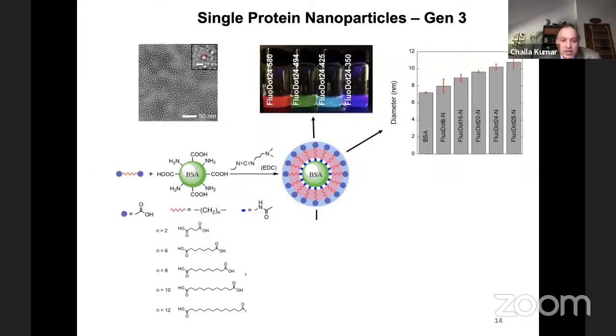Now she is working at Eurofins. So we changed the number of methylenes in our diacid systematically from 2, 6, 8, 10, 12, and so forth. And every time you do that, you're changing the diameter of the particle. And then you measure the diameter of the particle using a light scattering apparatus, and you correlate diameter versus the number of carbons you put in.